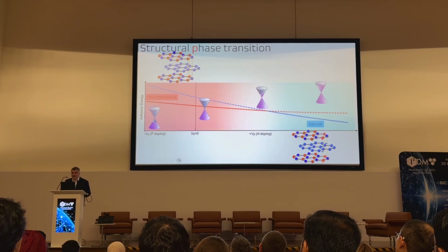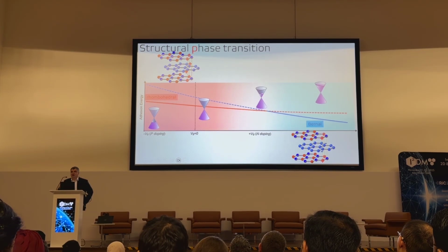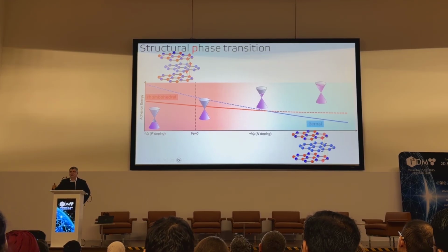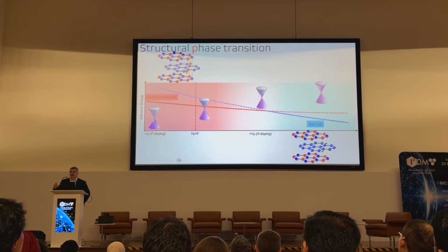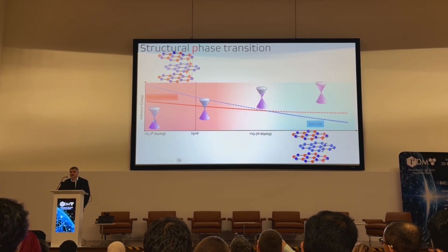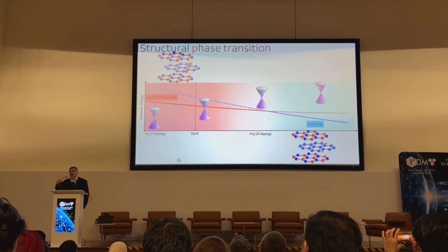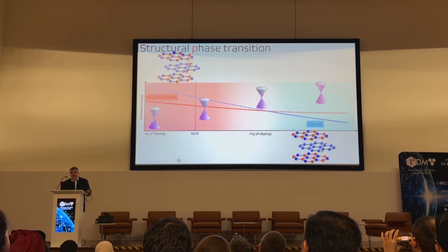So these configurations start to be more energetically favorable. Now on the left hand side there, again we have our boron being positively charged. But now if we charge graphene positively, so we have holes there, suddenly there is a repulsive interaction, which drives this state higher in energy, it becomes energetically unfavorable, and it wants to switch into the other one.